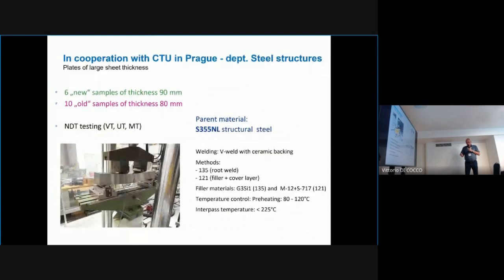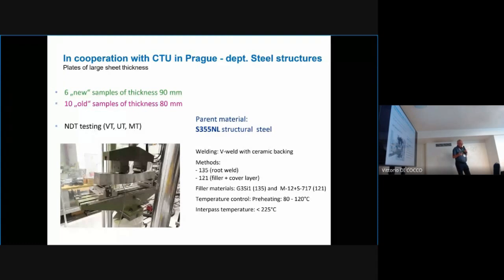In cooperation with Czech Technical University in Prague, we investigated plates of a large sheet thickness, because in collaboration with Škoda Transportation, we investigated the thicknesses 6, I think 12 and maybe 15 millimeters. And with Prague, we investigated experimentally samples of thickness 90 millimeters and 80 millimeters. The specimens were produced of this structural steel. You can see some information about the welding. I'm not an expert in welding, so I will not comment on it.